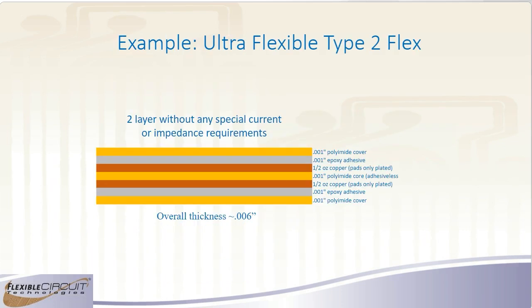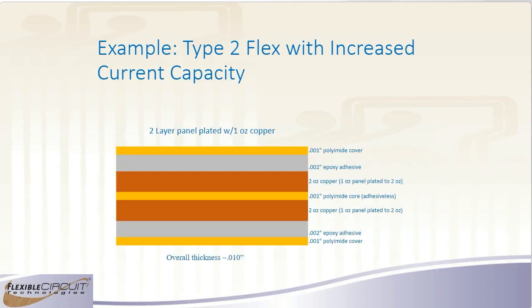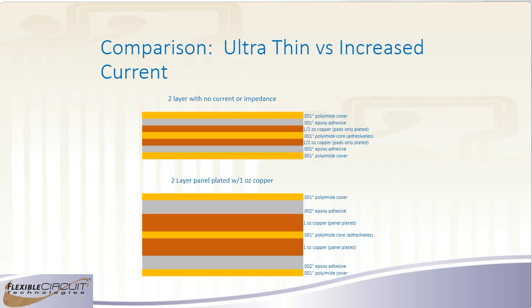An example, this would be a cross-section of just a standard two-layer flex that doesn't have any impedance or current requirements. And if we just use our standard materials, we're looking at about 0.006 of an inch overall thickness for a two-layer part. Now, if you throw in, say, 2 or 3 amps of current on some of those traces, now we have to go with 2-ounce copper in order to carry that current. In addition to the 2-ounce copper, you're also going to have 2-mil adhesive to be able to encapsulate all the traces. So when it's all said and done, you look at the difference, you can see that you've over doubled the thickness of the circuit just because you had higher current traces on one of the layers. So it's important to look at how that's going to affect, and like I said, it's going to be a lot stiffer when you have the high current traces.